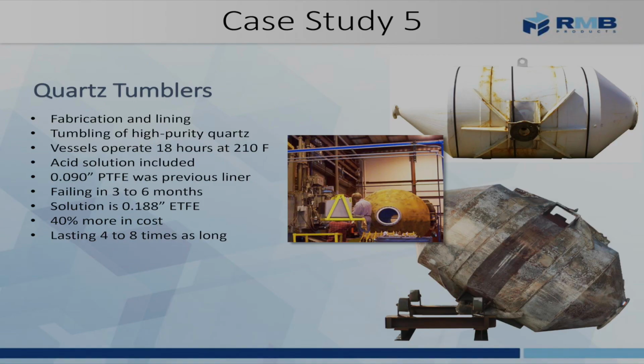And this is one of those that doesn't last 20 years. It's a quartz tumbler. It's very abrasive. It's got an acid media in it. And they were getting 3 to 6 months using a PTFE liner. And they found out about ETFE rotolining and are now just standardizing on that approach. So they're getting 2 years, 3 years, still not a full 20 years, but better than anything else they could find on the market to stay up and running. As this is one of the more aggressive services that rotolining would be serving.